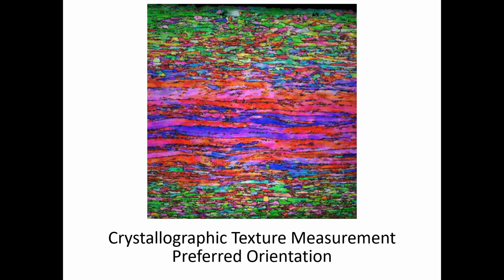And so similar colors mean similar orientation. And I think what's also important about this image is this is a typical JR material. And what you can see here is that the grain structure is finer on the surface than in the center. So this is the reason why sometimes the Charpy test actually passes the J2 requirement.